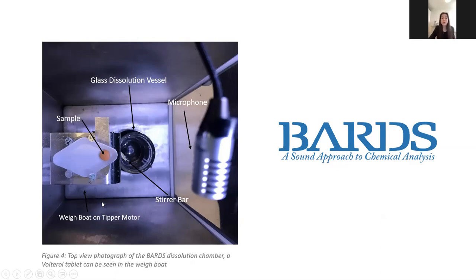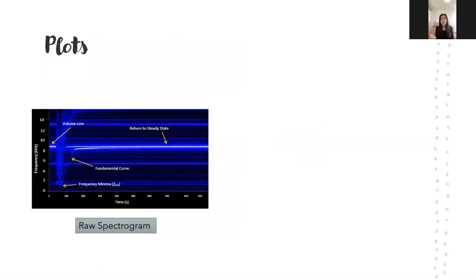So the sample is automatically introduced to solution after 30 seconds once a volume line resonance frequency has been established. The microphone records this change in frequency associated with the sample dissolving in the solution as the stir bar taps off the glass vessel. The magnet that stirs this stir bar is set off center to enable this tapping required for a BARDS spectrogram. So what is a BARDS spectrogram? What does it look like? So you can see here a typical raw spectrogram from the BARDS instrument.